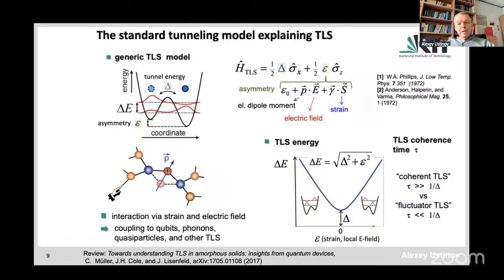One of them corresponds to the situation in a symmetric well, and is characterized by the tunneling splitting delta. And the second term corresponds to the asymmetry of the well. It was realized a long time ago, studying glasses, that you can influence this asymmetry by either applying an electric field or applying strain to the system. So you produce a tiny deformation of this lattice, either mechanically or by applying an electric field, and therefore you could change the symmetry of the two wells. So you could look at these defects as a kind of microscopic dipole, which interacts with strain and electric field. And obviously, this kind of defect will be coupling to qubits and phonons and all kinds of excitations in superconductors, including also quasi-particles and other two-level systems.